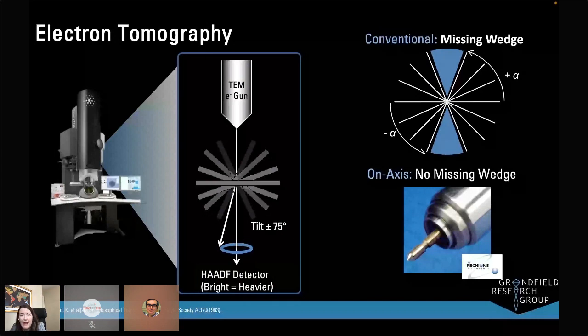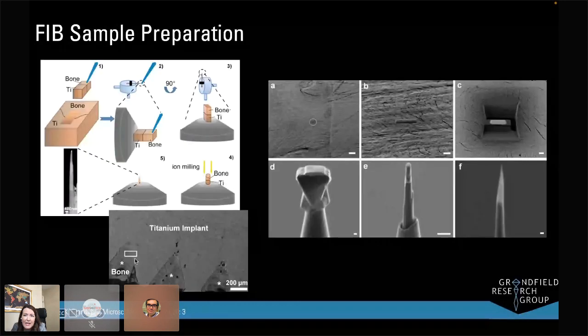So to do that, we go back to our focused ion beam, we identify an area we're interested in, and instead of taking our lift out and milling it as a rectangle, we begin to mill it into a cylinder and make quite a thin cylinder that we can put back into the transmission electron microscope, and now have a needle that we can rotate and perform some other chemistry on because it's a uniform thin needle.